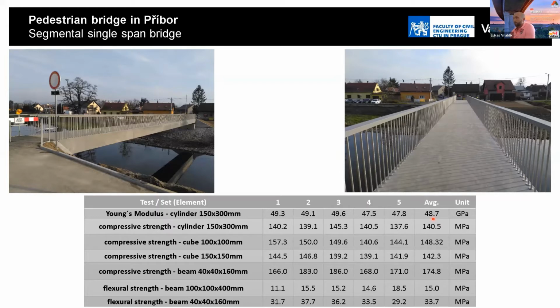Very interesting is the question about the flexure strength, because for the normal beam, with a cross-section dimension of 100 millimeters and a length of 400 millimeters, we obtain 15 megapascal. But for the smaller beam, again with 40 millimeters for the cross-section and 160 millimeters length, we obtain 33 megapascal. Again, comparing normal concrete, completely new material, completely new idea.